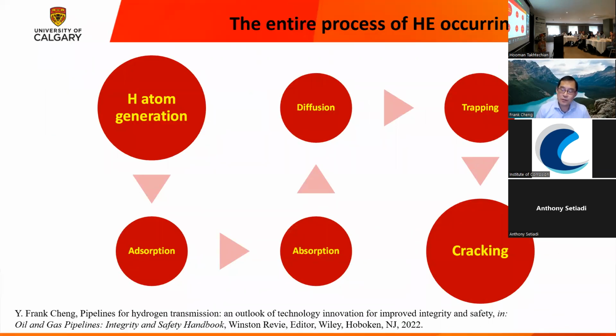Okay, for hydrogen embrittlement to happen, it usually includes 6 steps. So this is the entire process. Firstly, hydrogen atom must be generated in the environment. After hydrogen atom is generated, it will adsorb on the external surface of the metal. So we call it adsorption. And then the next step is adsorbed hydrogen from the outside going into the inside of the metal. From adsorption it becomes absorption. So we usually call it ADS hydrogen and ABS hydrogen.